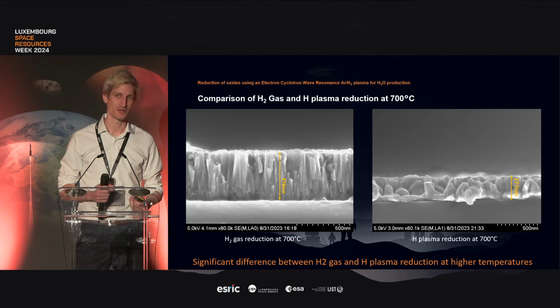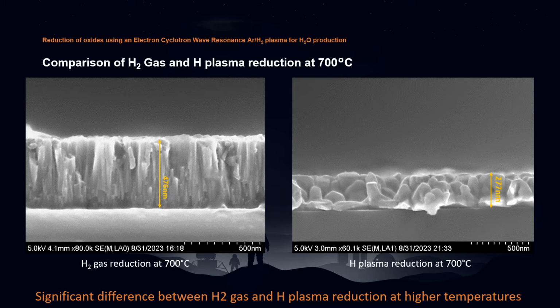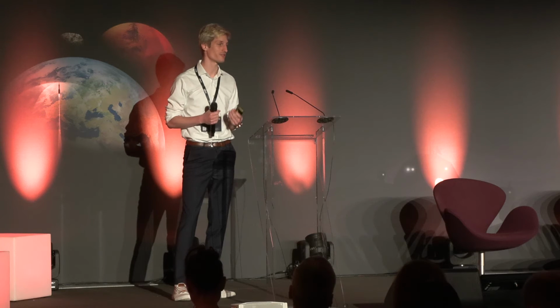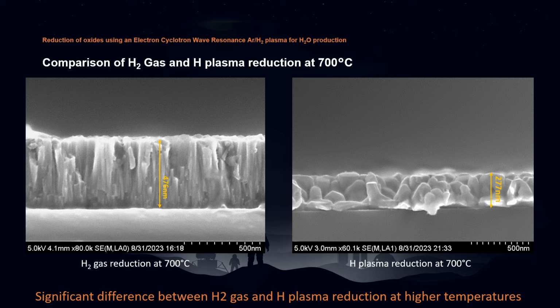We can see on the left side that there is some merger of columns and some slight indication of morphological change, but the story is completely different on the right side, as we see these coalescing islands, these stone-like features. What is left actually is this metallic iron that is trying to coalesce into a layer of metallic iron. And basically, when you look at these differences in the thicknesses or the heights between the left and the right image, this basically tells you how all of that oxygen was extracted.